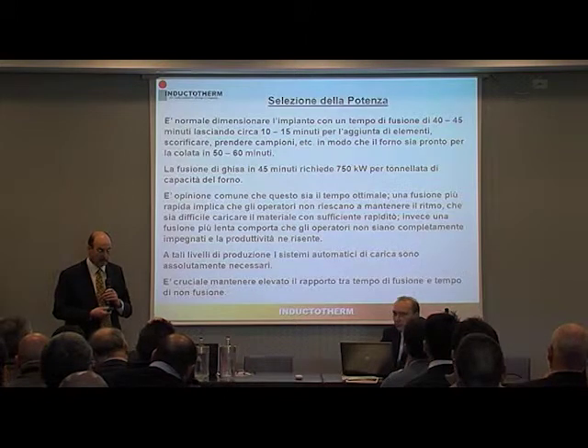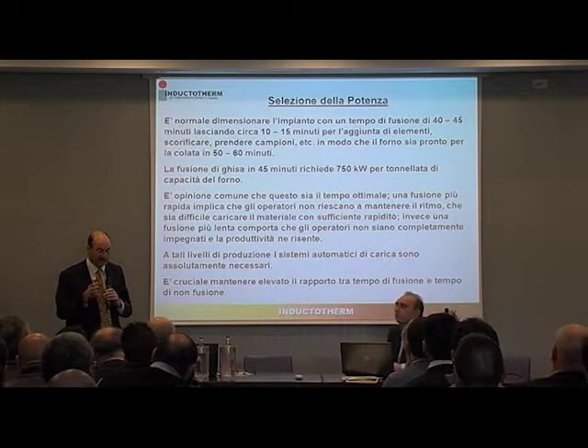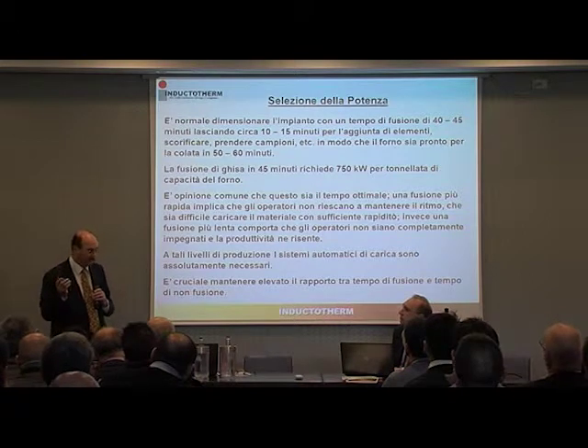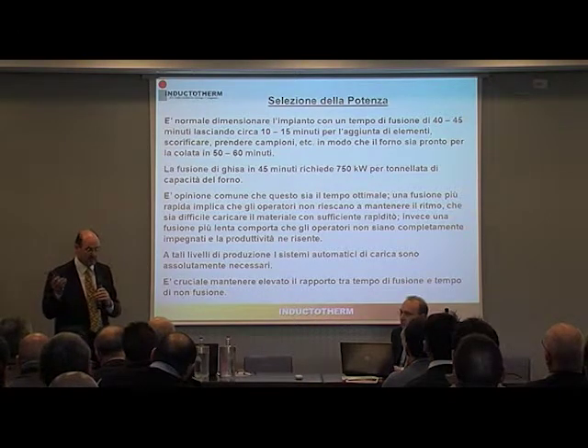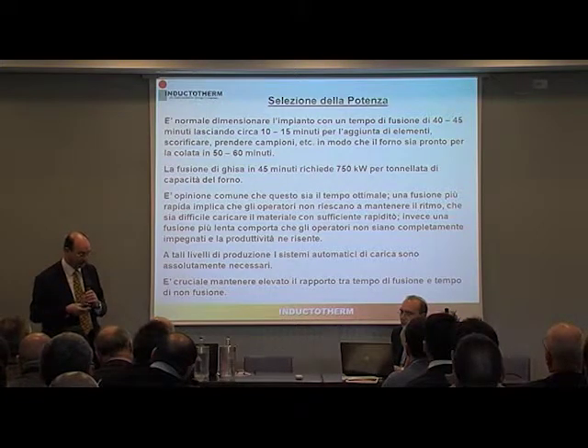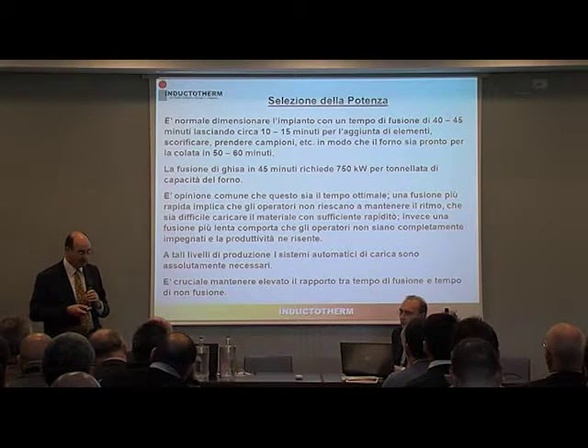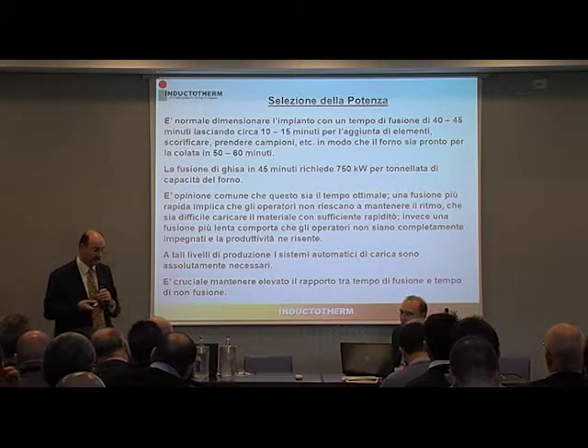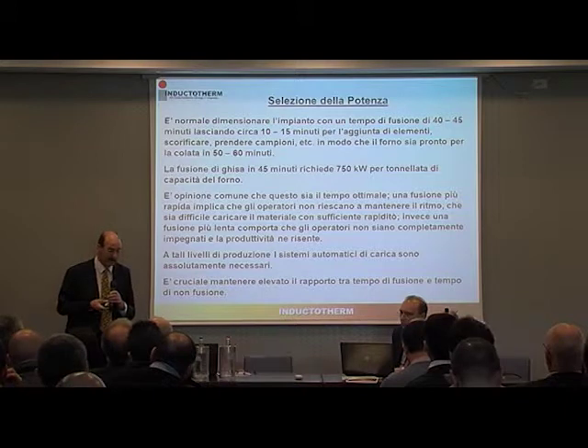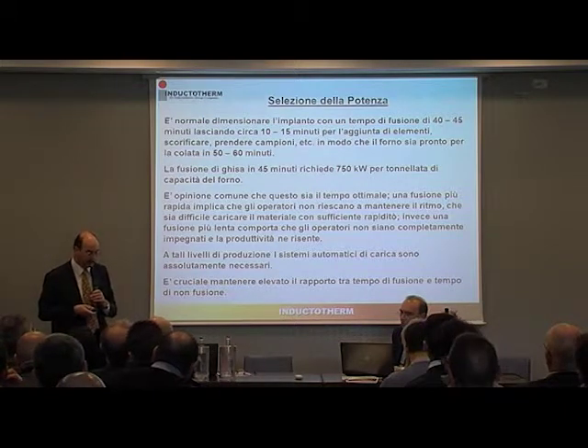Today it's more common to select equipment on the basis of a furnace will melt in 40 to 45 minutes, leaving approximately 10 to 15 minutes for alloying, slagging, sampling, and have the furnace ready to pour in about 50 to 60 minutes. 45-minute melting times require 750 kilowatts per ton when melting iron. So the furnace is no longer the limit of the power, the production becomes the limit of the power.